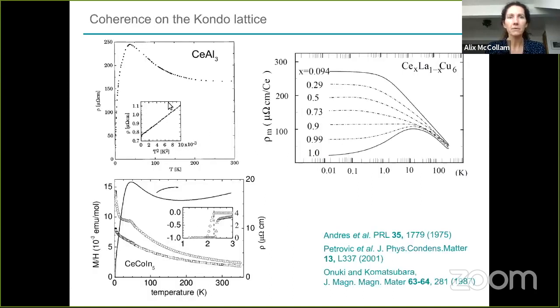So to see how that looks, these are some examples, kind of famous examples, I suppose. This is cerium aluminium 3. Resistivity doesn't do very much. This is resistivity as a function of temperature. It doesn't do very much at high temperature, and then you see it starting to increase due to the stronger interaction of the F and conduction electrons, and then the coherence starts to develop once you get to this Kondo temperature, and then below that the resistivity drops away.